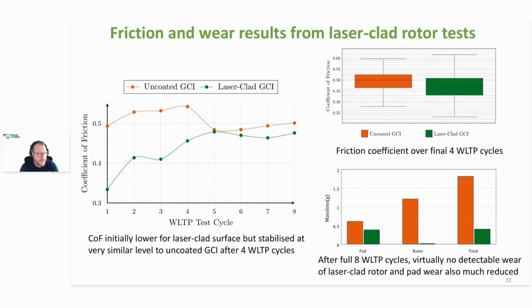Okay, now looking at the friction and wear results for the full 8 WLTP cycles conducted, we can see that the laser-clad rotor took more cycles to reach roughly the same coefficient of friction as the gray cast iron. So we can see there to WLTP cycle 5, the coefficient of friction cycles are very similar. And it may be that it takes longer for the laser-clad surface to establish a stable transfer layer, a fact that could be of concern for brake suppliers whose systems are expected to work perfectly from the first brake application.